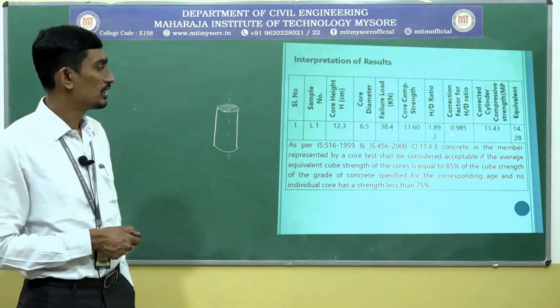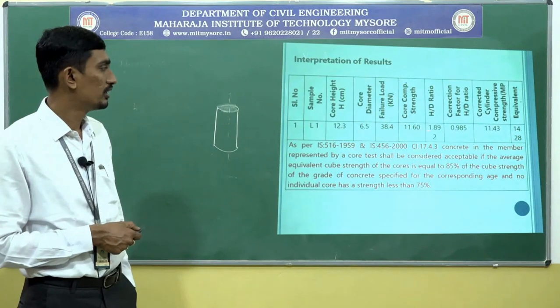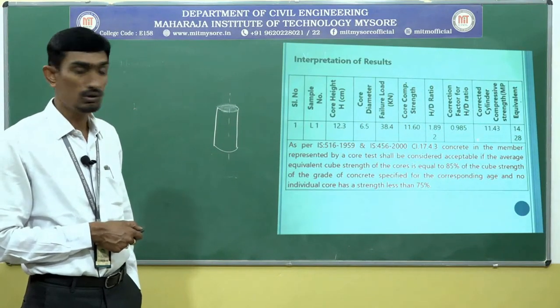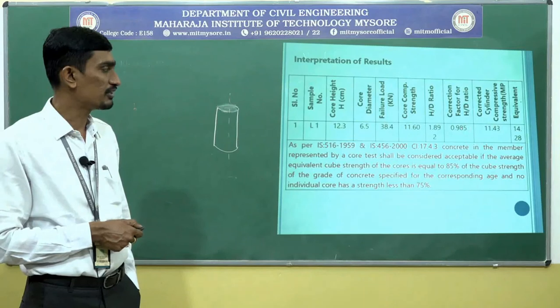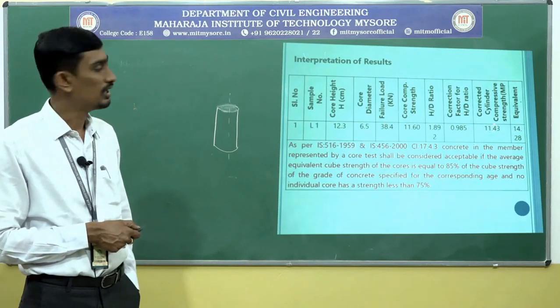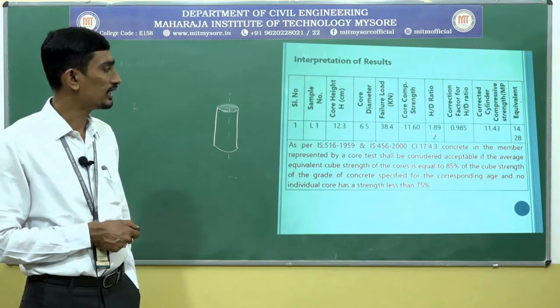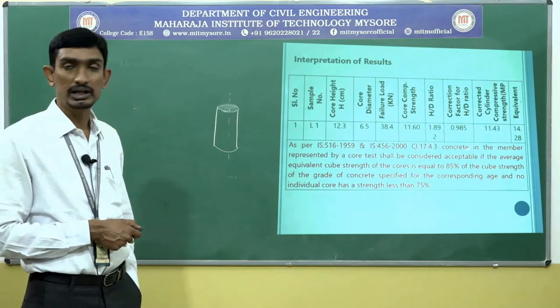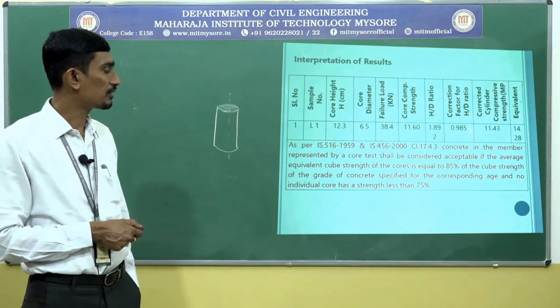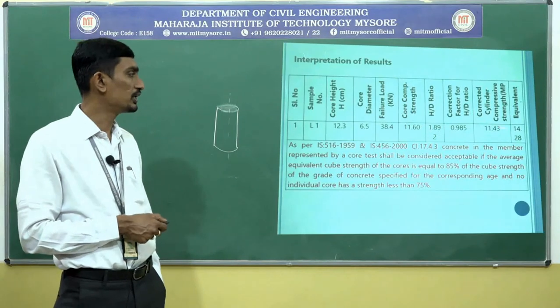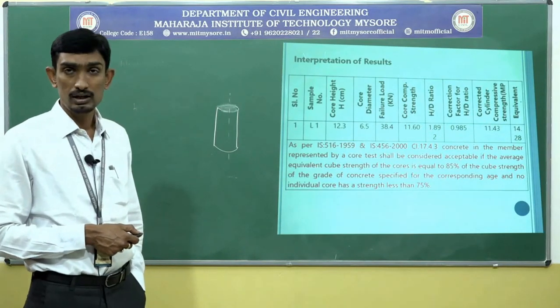Okay, why? Because the L by D ratio is 1.89. If it is 2, we need not apply any correction factor, that means it will be equal to 1 only. But since it is 1.89, the correction factor will be 0.98. So the correction factor multiplied by the core compressive strength will get you 11.43.